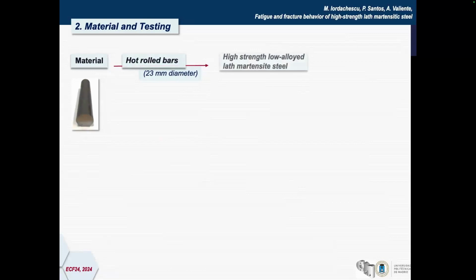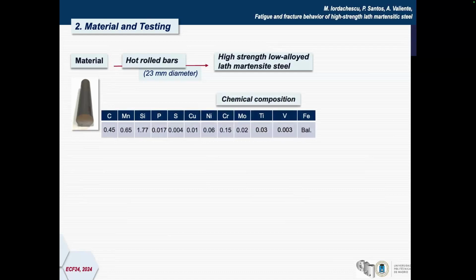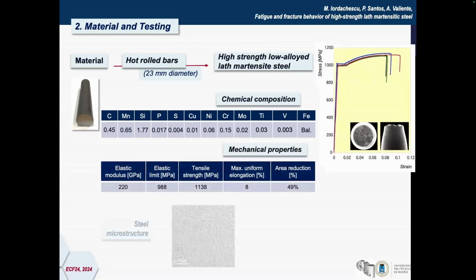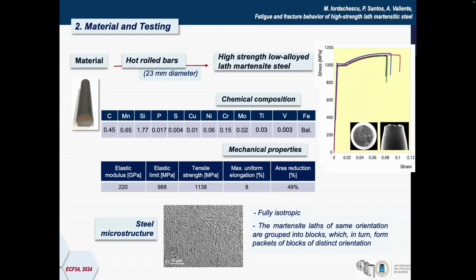Now, related to the material, it belongs to hot rolled bars, 23 millimeter diameter, with a chemical composition which shows us that we are dealing with a medium carbon steel, but with a lot of microalloying elements like copper, nickel, chromium, and molybdenum. With mechanical properties, tensile strength higher than 1,100 megapascals and elastic limit around 1,000 megapascals. Related to the steel microstructure, it is lath martensitic, and we found that it is quite fully